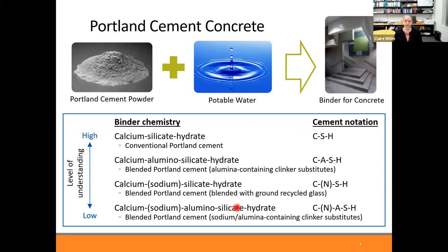And so, for example, if you add in a glass, or, well, a good example actually is calcined clays, and specifically calcined kaolinitic clays. There's a lot of aluminium that comes along. And so what happens is the composition of the gel changes, and so does the structure of the gel. So we have somewhat of a good understanding of this CASH gel, but not as much as the CSH gel. And so if we continue going on with other elements, sodium, for example, you can get this CNSH gel. Well, sorry, the CSH gel with sodium in it. And then also when you have sodium and aluminium, you get this CNASH gel. So we really need to understand what impact the additional elements have on the structure of this gel, and also how the thermodynamics of the gel changes.